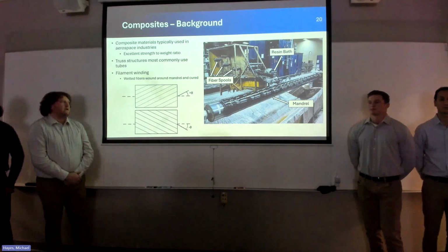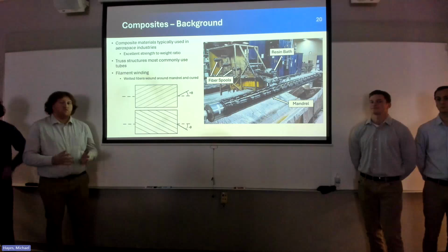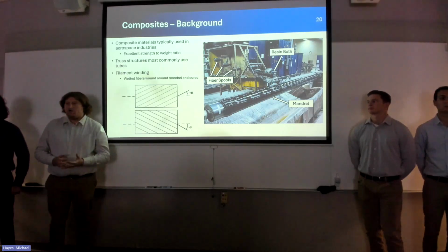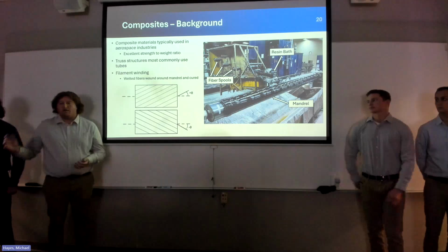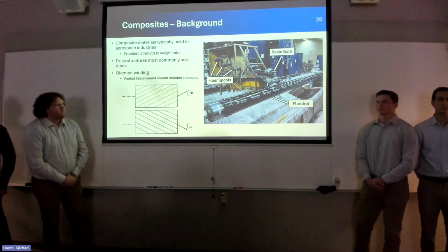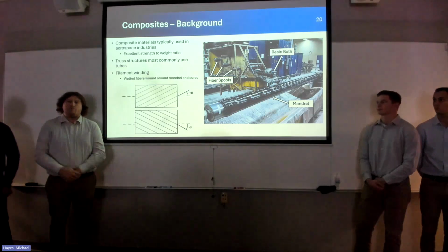One limitation of a filament winding process is that you must lay down a positive theta wind angle and then a negative theta wind angle before you change that wind angle. In other words, if you wanted a 30-degree wind angle, you must have a positive 30, then a negative 30, and then you can change that wind angle. Another limitation of filament winding is you must typically stay within a range of plus or minus 30 degrees to plus or minus 60 degrees.